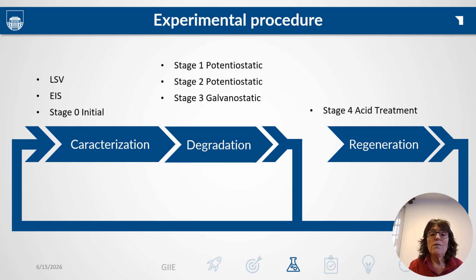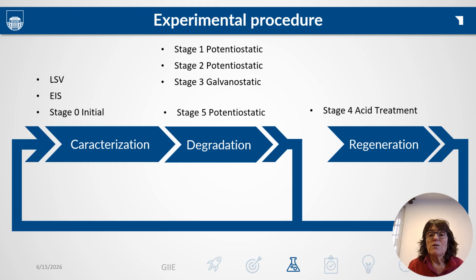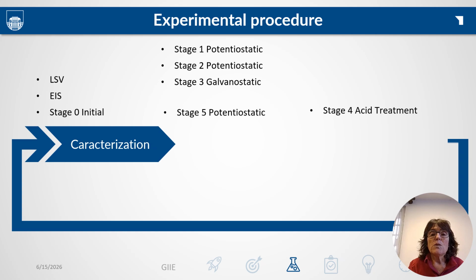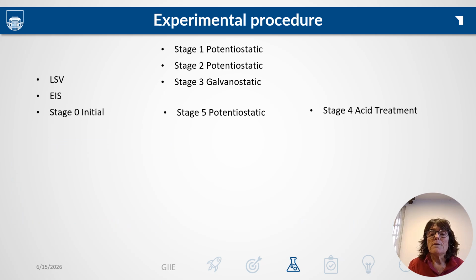And stage 5 is the final potentiostatic degradation step at 2 volts for another 168 hours, the week, designed to assess the durability of the regeneration. Between every stage, we perform the full electrochemical characterization sequence: cyclic voltammetry, linear sweep voltammetry, and impedance. This allows direct stage-by-stage comparison of degradation, recovery, and